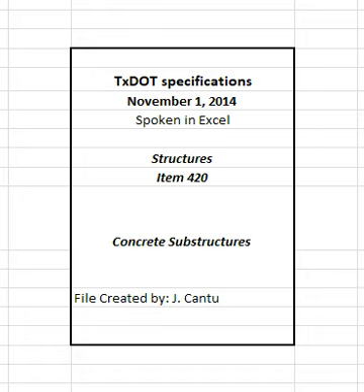Place Class A, B, and D concrete only when its temperature at the time of placement is greater than 50 degrees Fahrenheit. Place mass concrete in accordance with Section 420.4.7.14, Mass Placements, only when its temperature at the time of placement is between 50 degrees Fahrenheit and 75 degrees Fahrenheit. 4.7.2 Transporting time. Begin the discharge of concrete delivered in truck mixers within the times listed in Table 14 of Item 421, Hydraulic Cement Concrete.